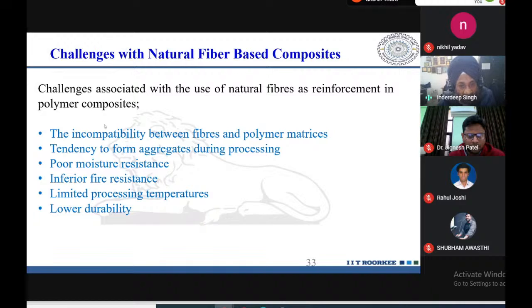They are hydrophilic in nature, whereas most of the polymers are hydrophobic in nature. So either we have to make the polymer hydrophilic so that they can have a good understanding with the fibers, or we can reduce the hydrophilicity of the natural fibers to make them compatible with the polymers. So that requires either the blending of polymers or the treatment of the natural fiber. So different strategies can be investigated to blend or to mix the fibers and the polymers to get good interfacial behavior that will lead to better or the best mechanical properties.